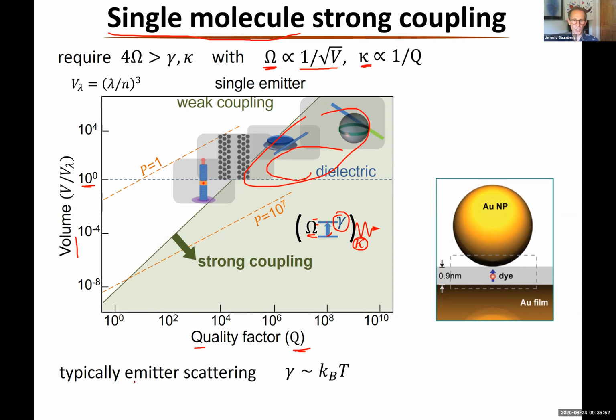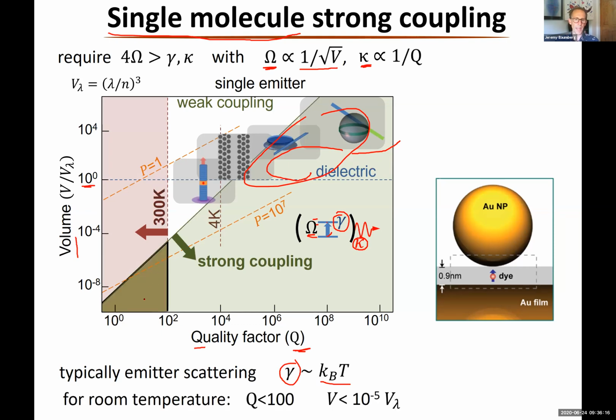Because the other thing that's important is typically at a temperature T, the interaction with a two-level system, this gamma, is always going to be around kT. In that case, kT corresponds to this sort of quality factor here. So that's why to get single molecule strong coupling in a dielectric system, you always have to cool the system down, and then you're not really doing interesting chemistry. To do interesting chemistry, you've got to be in this region here. So you've got to be in the strong coupling region and able to access it at room temperature. And that's where the nanoparticle emitter sits, or any very strong plasmonic structure. You need volumes which are less than 10 to the minus 5 of the dielectric volume.